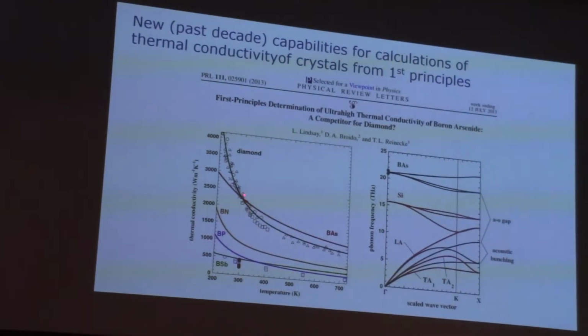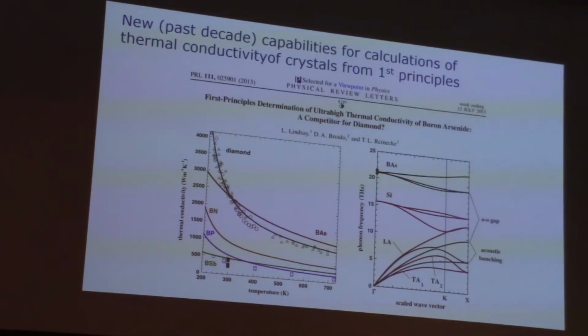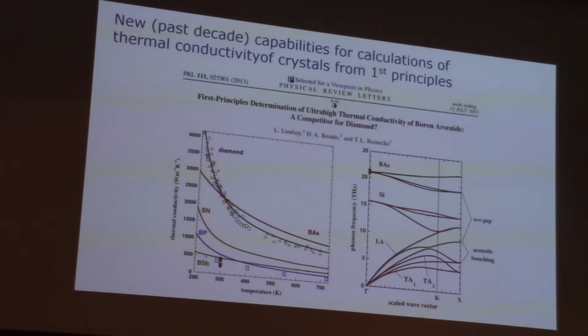He predicted that this crystal boron arsenide would have a thermal conductivity at room temperature about the same as diamond, and above room temperature would exceed the thermal conductivity of diamond. Right? That's a wonderful thing for a theorist to do, predict something that we don't expect. We certainly didn't expect this, because on average, its acoustic phonons kind of look like the acoustic phonons in silicon. And the only difference is that the optical phonons are pushed up in frequency. That's the critical thing. And the details of these dispersions are a little different. In silicon, it's much more spread out than it is in this boron arsenide. Anyway, so that was the prediction.